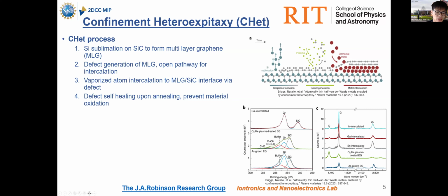And at the bottom is XPS and Raman data to show how the graphene progresses during the growth process. So we can start with XPS. Interestingly, you see all the peaks stick together, where the buffer graphene, the top layer graphene, and also the silicon carbide substrate. However, as you intercalate, you'll see this carbon peak splitting that confirms the decoupling of the graphene and the silicon carbide, which shows atom intercalation.